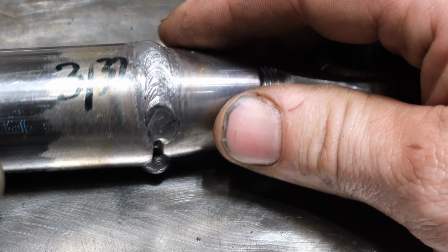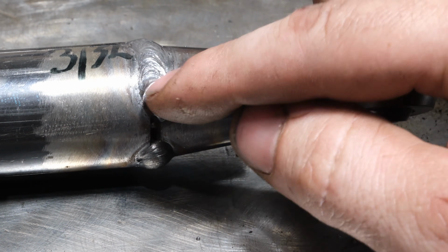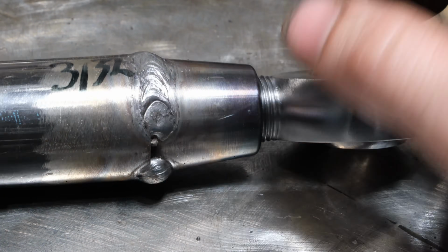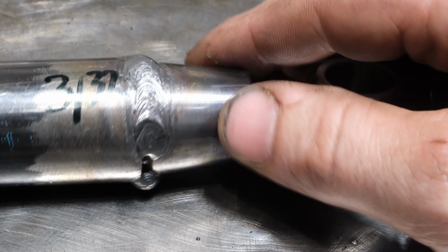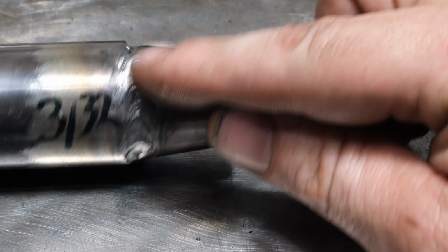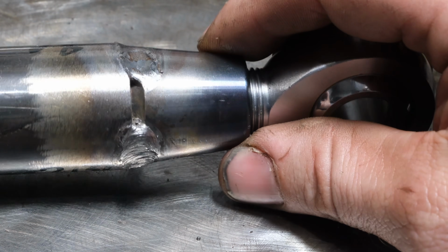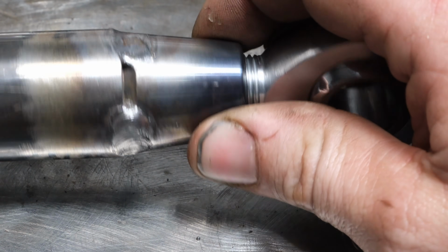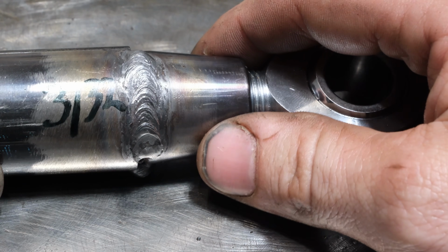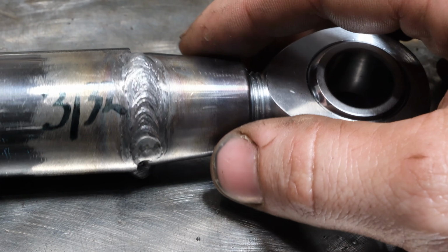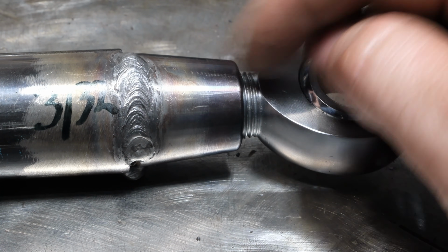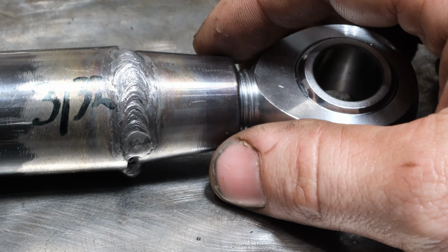Now, my travel speed near the end started picking up. Where I snapped out of it, there's a little bit of underfill, but hey, that's stick welding. You're going to have that. But if you can do anything even close to this, and I'll show you the bottom profile, I would say that you're going to have a strong weld, and it's highly unlikely that this would ever fail. More than likely, it would split and tear this out before this would fail.